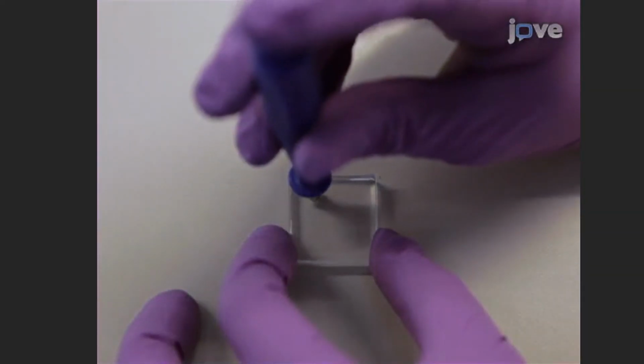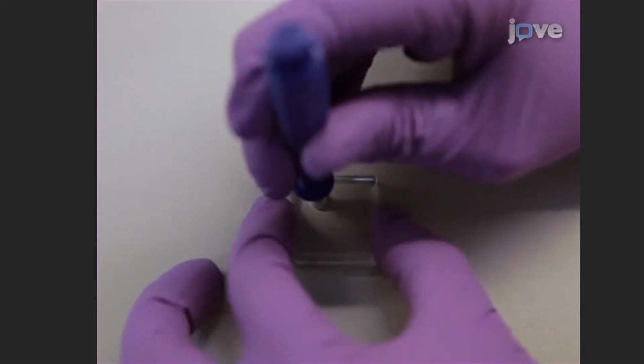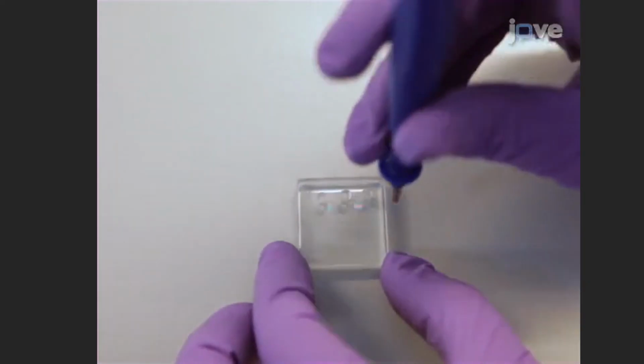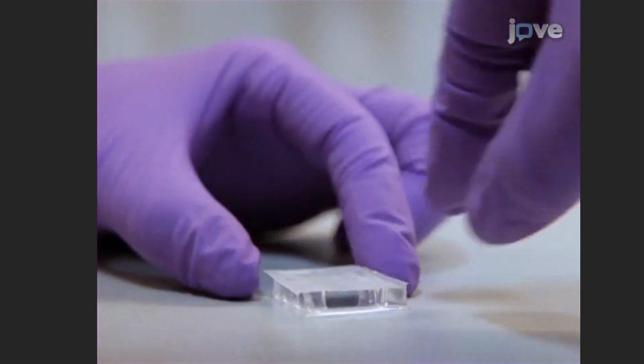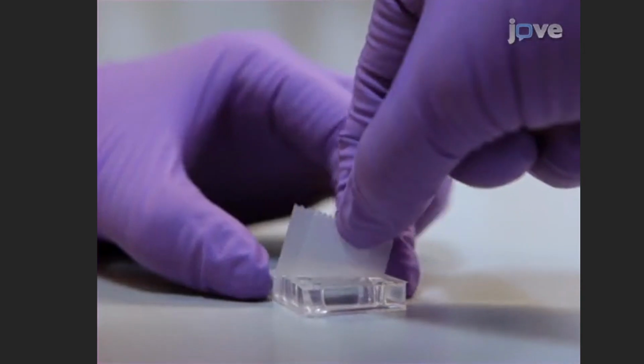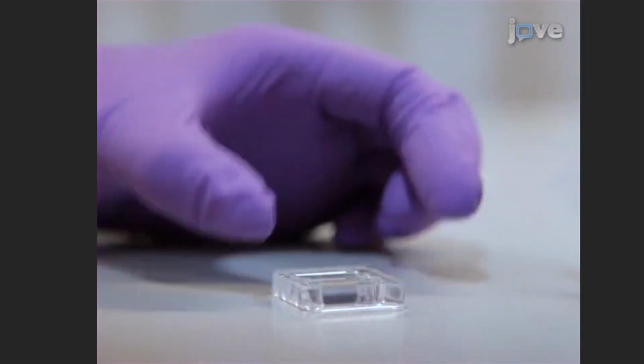Now, prepare the 6 interface ports using a 3mm biopsy punch, with the microstructured features facing upwards to aid alignment of the ports with the microfluidic channels. Inspect the device for particulates and remove them using reversible adhesive tape.